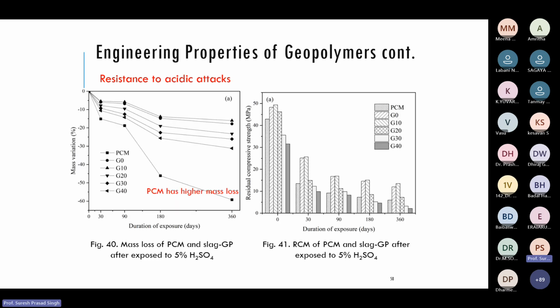Okay, next, resistance to acid attack. There is a lot of mass loss you see, and this is subjected to 5% sulfuric acid solution. So with a duration of 360 days, 1 year, we put it in an acidic solution of 5% sulfuric acid, and there is a continuous mass loss in this Portland cement mortar. But geopolymer has less mass loss. Here the mass loss is as high as 60% in Portland cement mortar, but here the mass loss is around 20 to 25%. And in this better one, it is only 12 to 15%. Again, a similar trend is there in the residual compressive strength. So geopolymers are more durable to all types of mechanical and chemical weathering processes or elements compared to the cement.